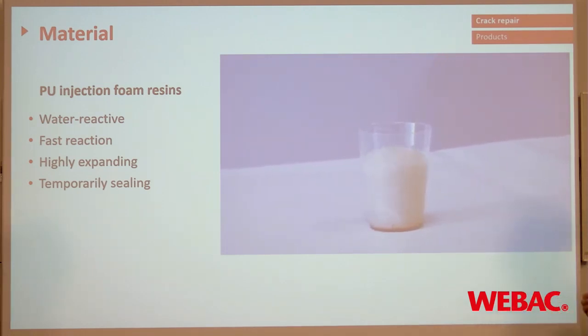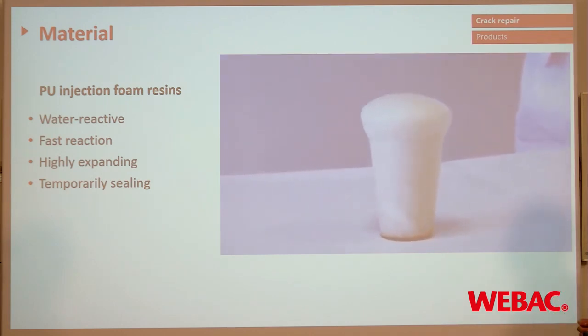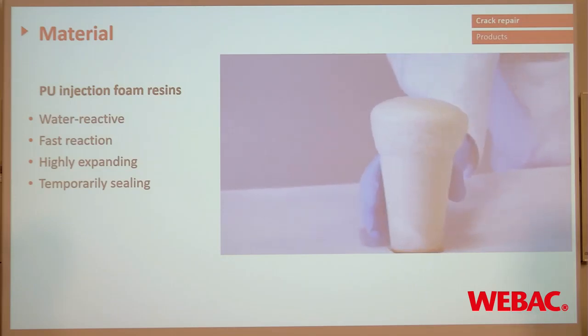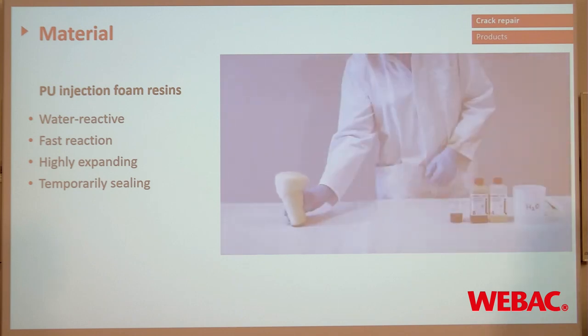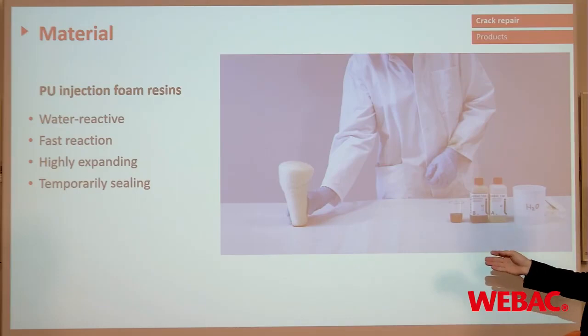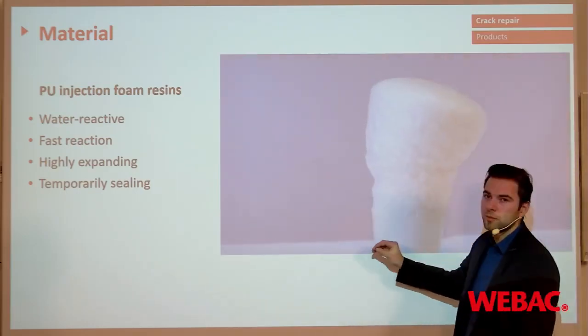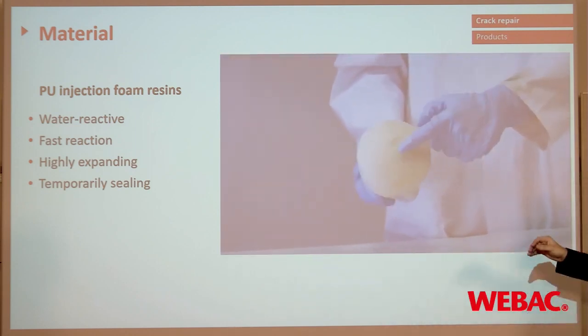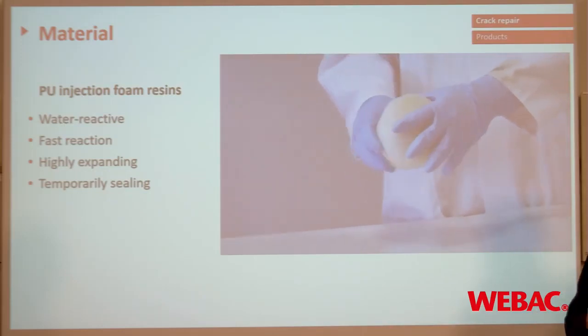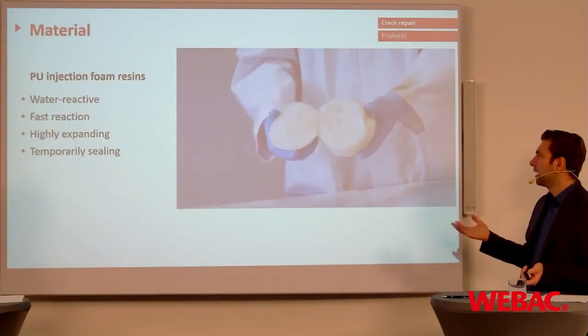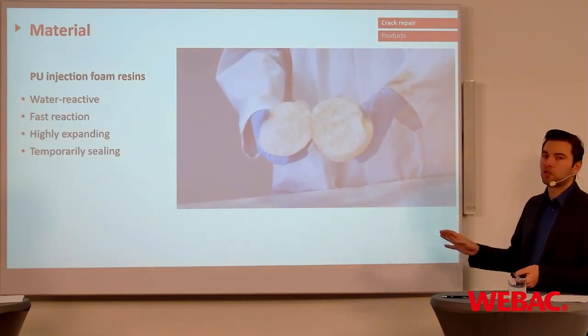Due to these properties, the high expansion, there is a lot of CO2 inside the foam structure, meaning you have small bubbles within the foam structure. In this foam structure, there might be the possibility of water penetration after a certain time. Therefore, it is only a temporary sealing, meaning you would have to carry out another injection with another material type to make it a long-lasting sealing. Maybe you have seen it in the meantime. It was a small amount of material, just some drops of water, and the expansion is up to 40 times. So it's very fast reacting, highly expanding. And as you can see, you have an even foam structure here.